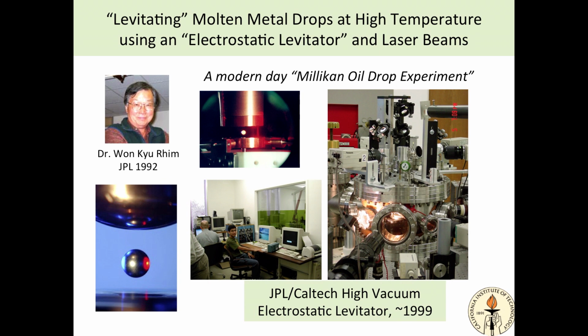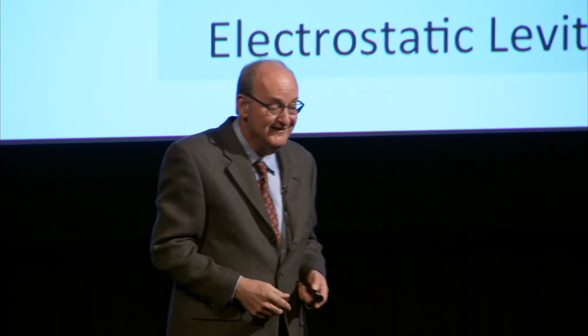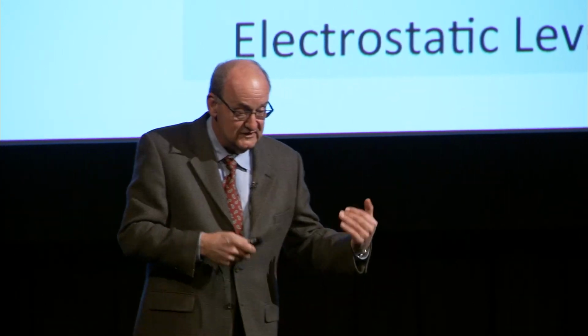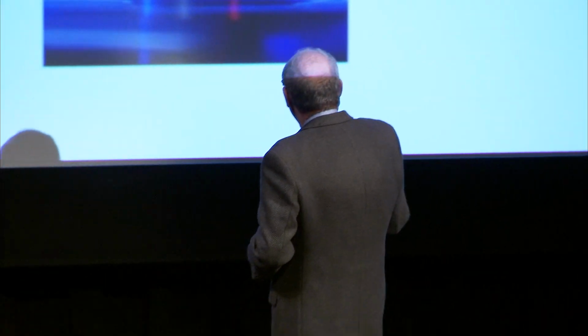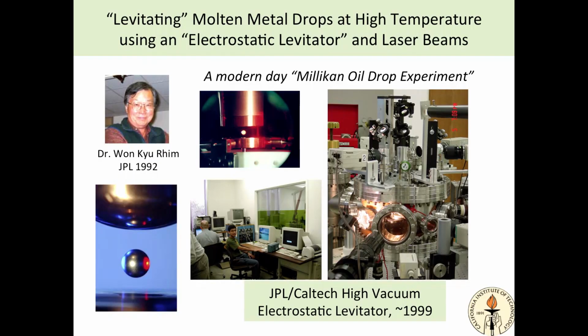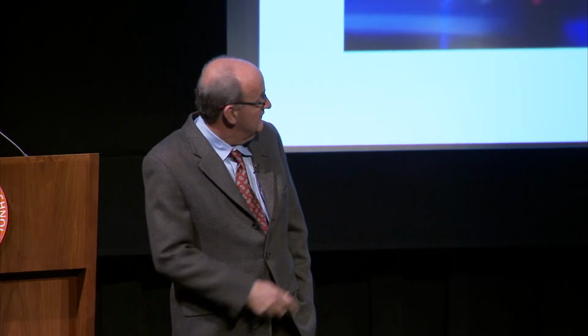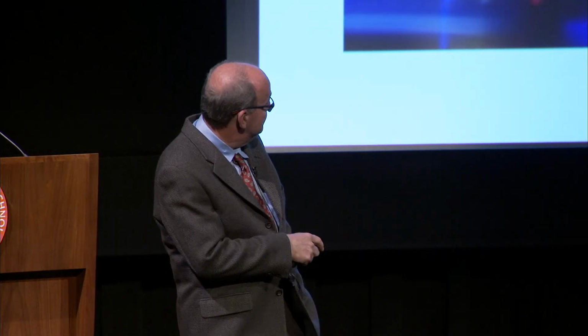You can ping the drop and watch it oscillate and back out the viscosity of the drop. You can see how it's becoming more viscous as you cool it. You can map the freezing curve. So we can go in and look and see exactly what's going on. So with the electrostatic levitator, there's a levitated ball of the vitrified alloy, the zirconium, titanium, nickel, copper, glass forming alloy, and it's sitting here at 1300 degrees centigrade, 2000 Fahrenheit, and it's in a vacuum chamber, and there's no container, it's just hanging out by levitation.